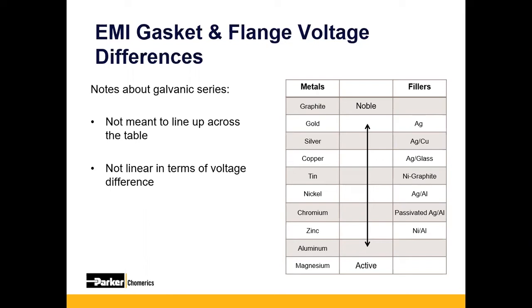And one thing I want to point out too is on the left, you see all the different metals in the chart. Most likely, you're not going to be able to get a pure copper gasket. If you look on the right at our typical fillers, you're going to have something that's a silver plated copper or a nickel plated graphite. So it's really important to pay attention to the metals with the fillers and try to minimize the galvanic corrosion, galvanic differences, and bring those closer together.